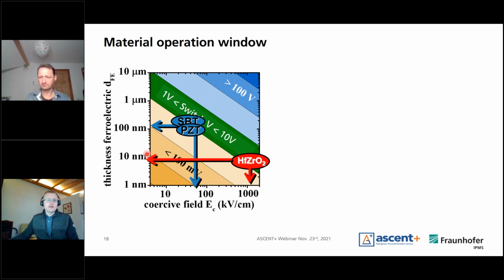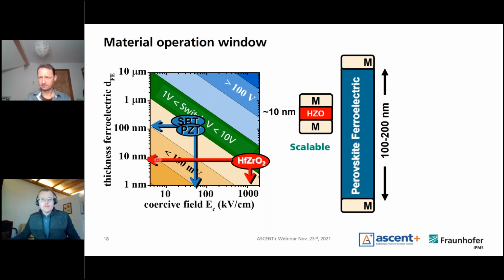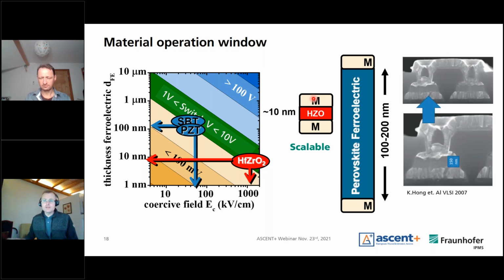So they can switch at around 10 nanometers already. In other words, it means we can scale the material and apply much thinner stacks, which also paves the path towards 3D integration. It's also an example from literature with a PZT-implemented FRAM concept, which has much thicker material thickness.